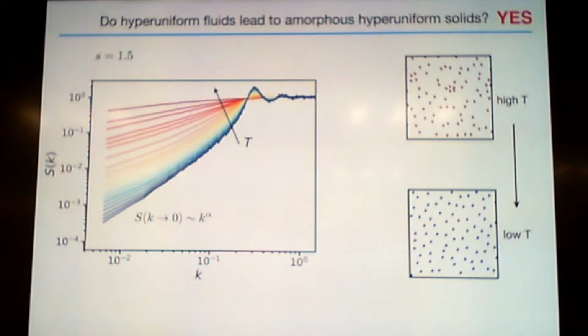So you have a liquid which you cool down, and you end up in a system which can no longer equilibrate, which we call glass, by that dynamic definition. And this glass is also hyperuniform. And I will show you in a second that this glass is different from the liquid from which it forms. So it is in a way like a phase transition. I mean, not a thermodynamic phase transition in the classical sense. There's no symmetry breaking, etc. But in a way, the glass is different from the liquid from which it forms, which is against the main idea of glass.